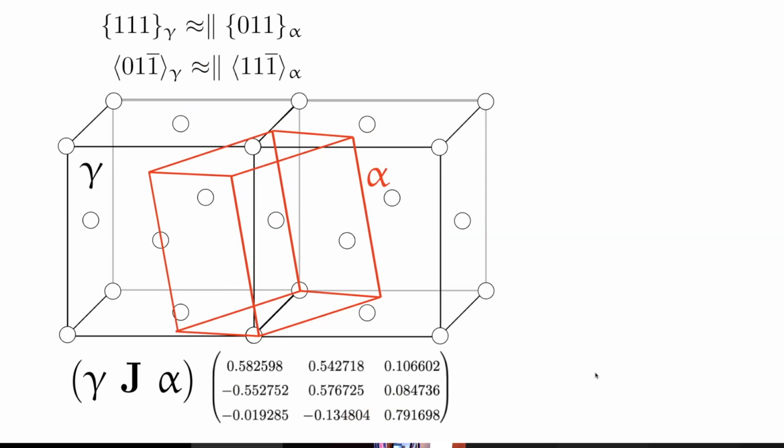If you look at those orientation relationships, the martensite cell is inclined to the austenite cell. But actually, those orientation relationships are approximate. They are not exact. The real orientation relationships are irrational. That means that we don't have exactly parallel close-packed planes from the two lattices. There is a small angle between them, and similarly for the directions.